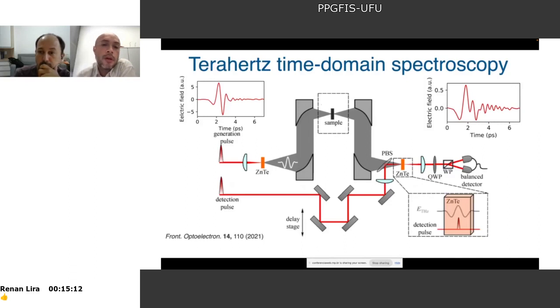Okay, this is the experiment. It's called terahertz time domain spectroscopy. In this experiment, we use the generation of terahertz pulses with pulse laser. So we use two pulse lasers, one for generation and one for detection. The laser for generation must have very high power, and then you shine this laser in a zinc telluride crystal, and you will have the emission of a terahertz pulse.